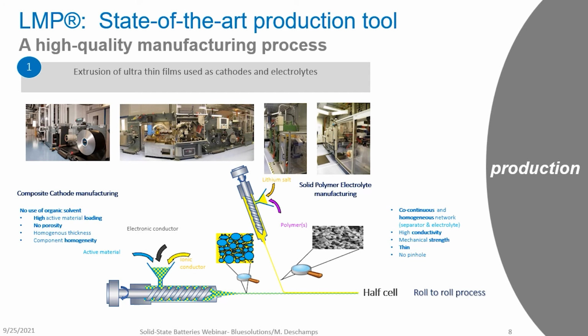A twin screw extruder is used to mix the raw material and to melt the polymer. We obtain a foil after the barrel. Then this composite electrode is deposited on the aluminum collector. We have to cover the second side of the current collector with the second cathode. What we want to achieve is high active material loading, no porosity, homogeneous thickness, component homogeneity.